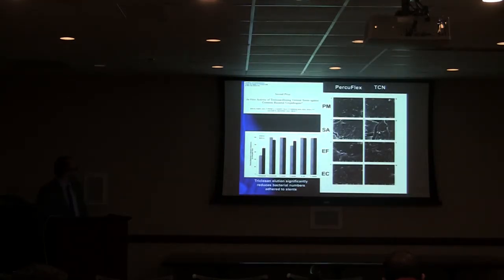This was then also repeated by another group, which again showed, and this graph shows percent reduction in bacterial adhesion. And again, you've got even Pseudomonas aeruginosa in this group, as well as Proteus mirabilis, and you can see again, at 40 hours and at 96 hours, highly effective at killing the bugs, which was nice. Pseudomonas didn't work as well, but that was mostly due to the fact that Pseudomonas is naturally resistant to certain concentrations of triclosan, so it wasn't necessarily surprising.